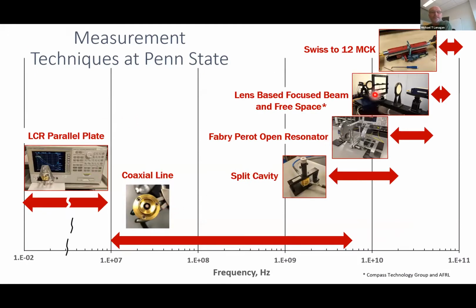So looking at all these different techniques, here we're looking at the frequency range in which these measurements occur, in this case starting at 10 to the minus 2 hertz. So we're at 10 millihertz, so very low. And as we go up 13 orders of magnitude in frequency, we can see that we move from a very straightforward parallel plate method all the way into all these different techniques shown here. And it takes a lot of work to measure these properties above a gigahertz. So whereas maybe 1 or 2 techniques was sufficient to measure properties down here, now we have many, many more techniques to develop to measure dielectric properties in this frequency range between a gigahertz and up to a terahertz. So this is our focus for 5G.